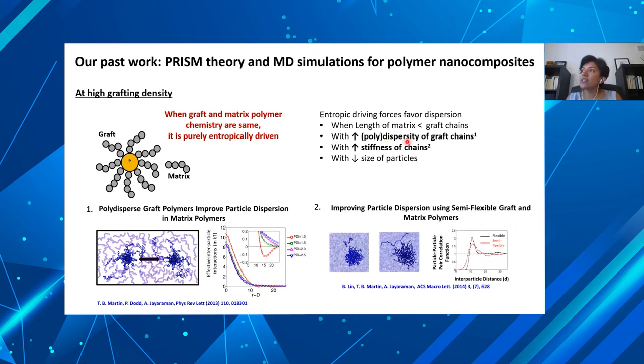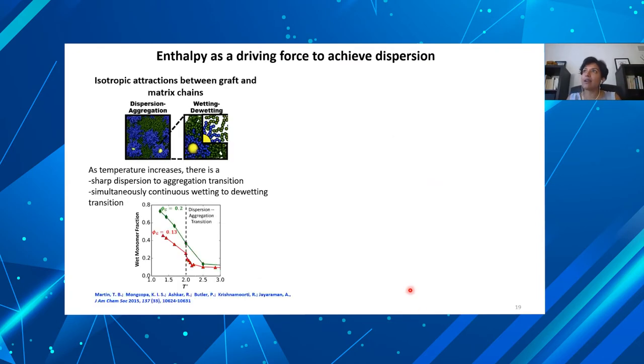We also found that changing stiffness, making things stiffer, so if you chose polymers with higher persistence lengths, you would favor dispersion more than lower persistence length. And similarly, particle curvature: if you chose smaller curvature, then you have higher chance for dispersion. That was all entropy. As I said, our goal is enthalpy and entropy. So what happens when you bring in different chemistries?